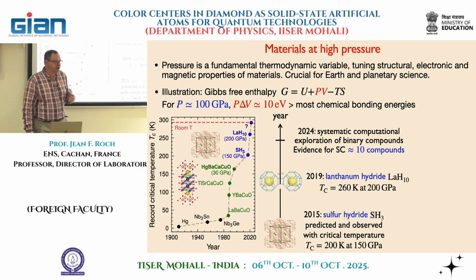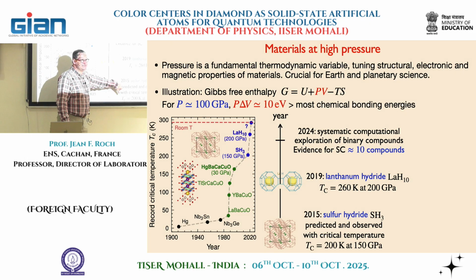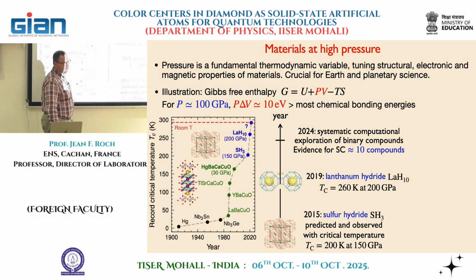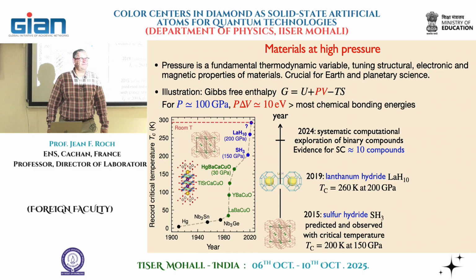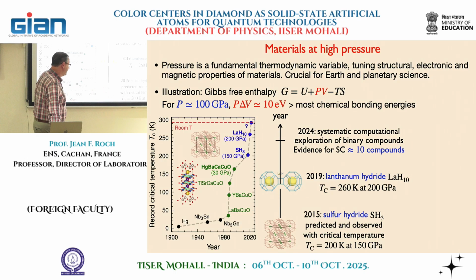And it was found that indeed superconductivity was first found by Michael Eremets and his team in Mainz in 2015, 10 years ago, in sulfur hydride. That was indeed predicted in this material by ab initio calculation, and it was observed using resistivity measurement. And that was a very landmark paper. The critical temperature immediately rises very significantly, 200 Kelvin at a pressure of 150 gigapascal. Of course, the question is, and I will discuss that at the conclusion, what can you do at such pressure? Is it an interesting material for any application at those pressures? Let's put that aside for the moment.